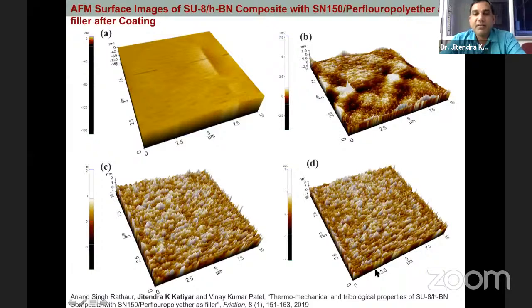And this can also help me in explaining the wettability test, because this surface is more hydrophobic in nature, approximately 100-degree water contact angle. So why do I achieve this 100-degree water contact angle? Due to this surface, I can observe that this nanotexture is present, and due to the structuring, the contact area is reduced, and it can increase the surface property, the hydrophobicity of that particular surface.